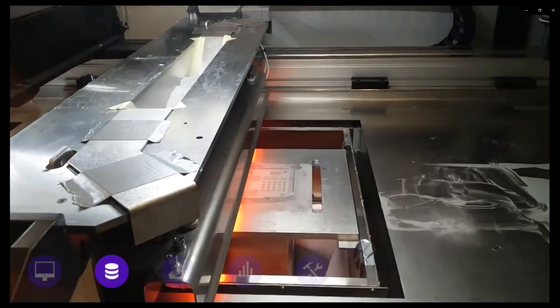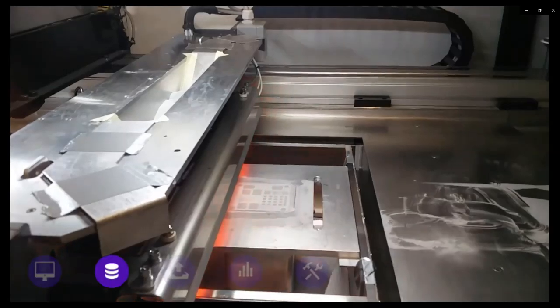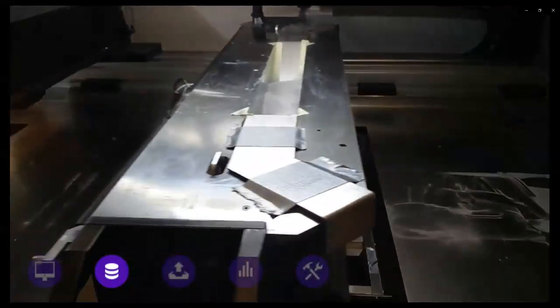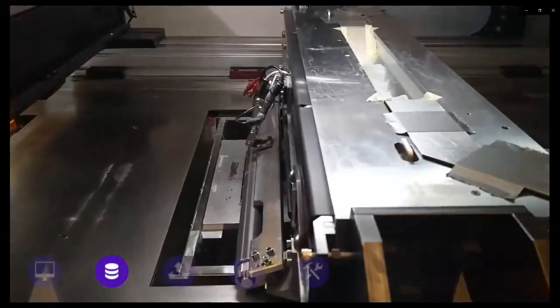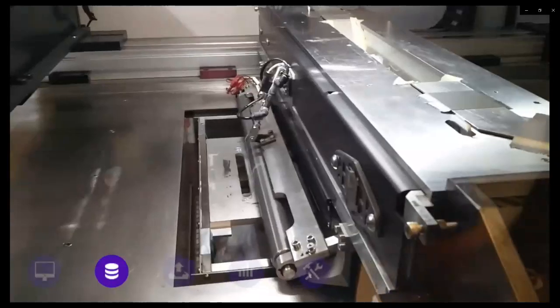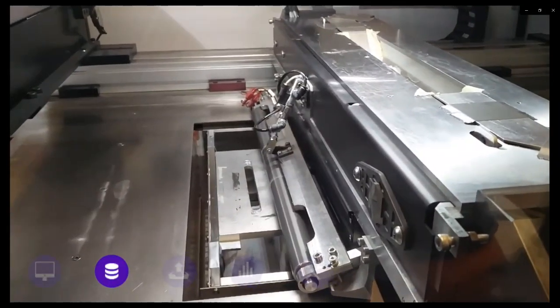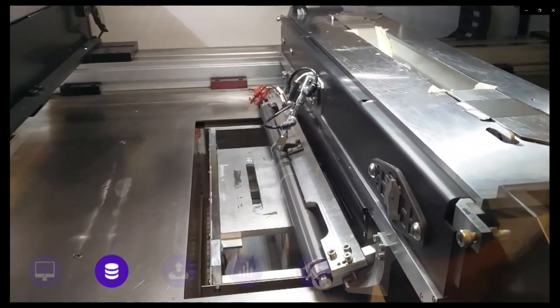Here, we see the previous layer being heated to cure the binder before a new layer of powder is spread. Then, the powder is dispensed from a hopper system at the top onto the build area, where a roller spreads it uniformly across the layer.